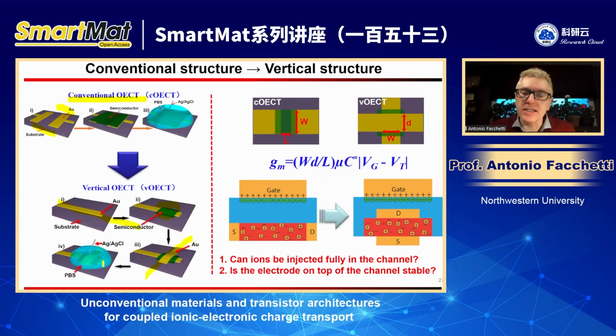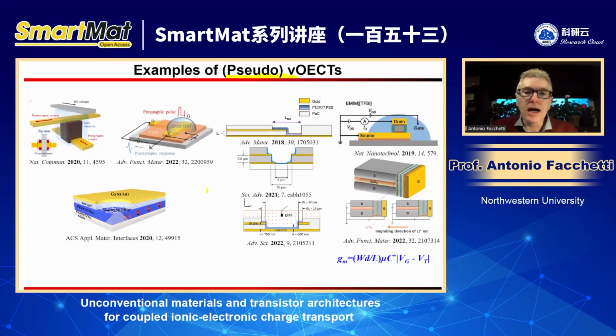Obviously, the obvious question is, if you put two electrodes on top of each other, the ion has to penetrate here. So the question is, can the ion be injected? This is what is challenging in a vertical OECT. Also in an OTFT, a vertical architecture has been made, but you need to use a porous electrode. There are some examples of pseudo VOECT, but not really truly OECT. For example, if you look at this architecture, this is called a vertical architecture, but in reality, the charge transport is planar. It's just vertical contacts, but the transport is completely planar. This is true for many other devices because the challenge is to get the ion to penetrate into the contacts.